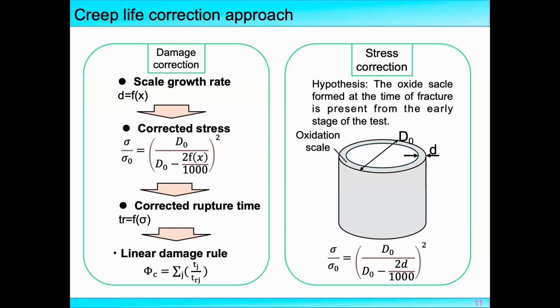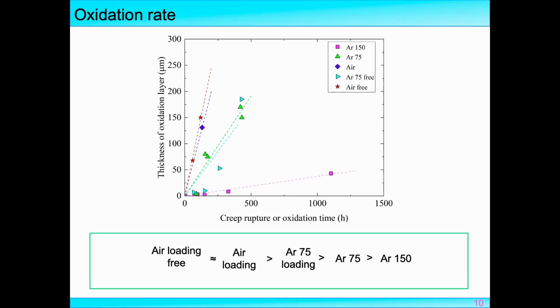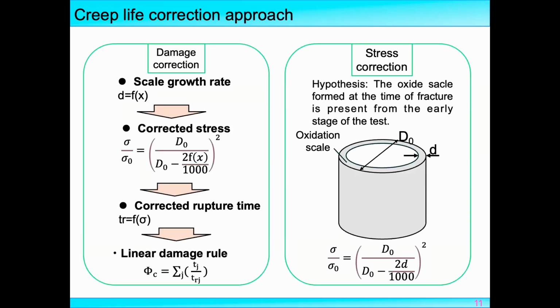After that, we corrected the creep life using 4 methods. One we call the damage correction. Here we can see the method given here. First of all, we calculate the scale growth rate by using this graph for the corresponding test condition. And then we correct the real stress by using this curve. The illustration is given here. After that, we calculate the relative creep rupture time. Finally, we use the linear damage rule to calculate the damage. When the damage becomes 1, we think that the creep fracture occurred, and the corresponding life is the corrected creep life.